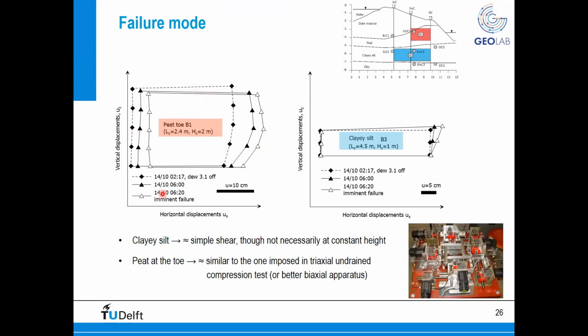So here I want to show you, on the left-hand side, the block of peat. You can clearly see that the failure mechanism is described by a very important lateral bulging. You see that the dashed line is the initial shape of the block of peat. And if you follow the deformation mode, you see that the block of peat bulged horizontally due to the very high compressibility of this layer, followed by a small vertical squeeze. At the same time, the behavior of the clayey silt layer is completely different. By combining again the lateral displacement and the vertical displacement, we could see that the clayey silt layer behaves similar to a direct simple shear test, but however, there was a small dilation. So it's a direct simple shear test, not at constant height.